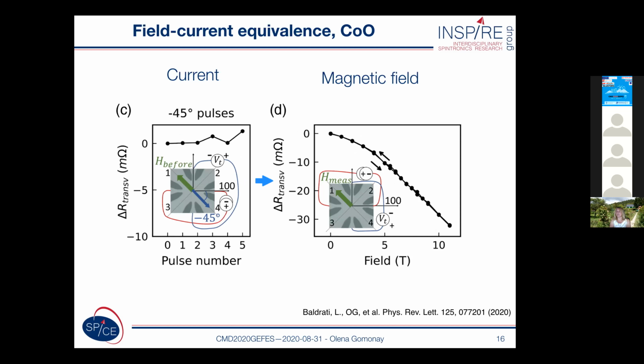So this means that current acts similar to the magnetic field and switches the Néel vector only in one orientation. So one orientation is unstable, the other is stable. Current removes degeneracy between two orientations. But the surprising thing in this case was that for cobalt oxide, in contrast to nickel oxide, the final state of the system was the state in which the Néel vector was perpendicular to the direction of the current. And this switching cannot be explained by the spin-orbit torque mechanism, which always predicts orientation of the Néel vector parallel to the current. So it was a challenge,